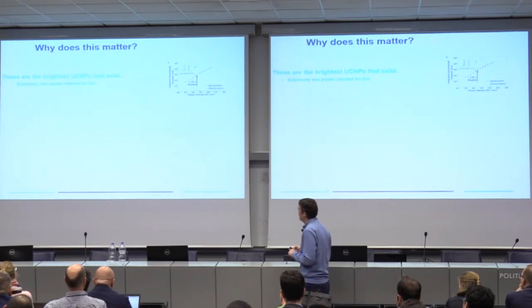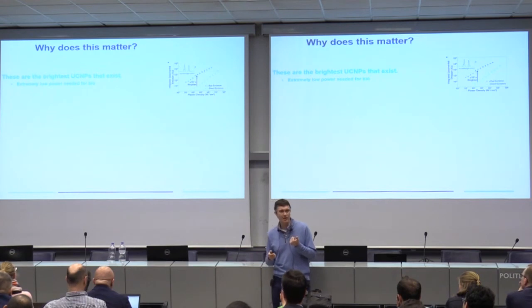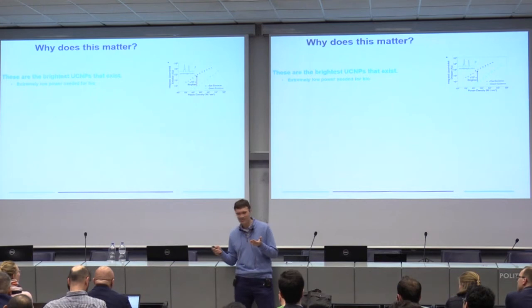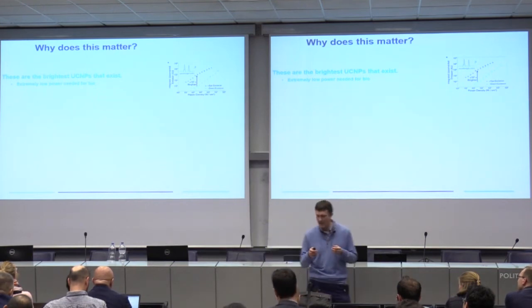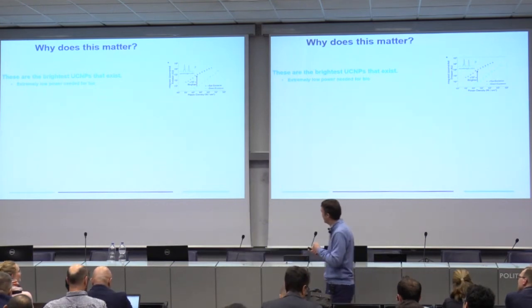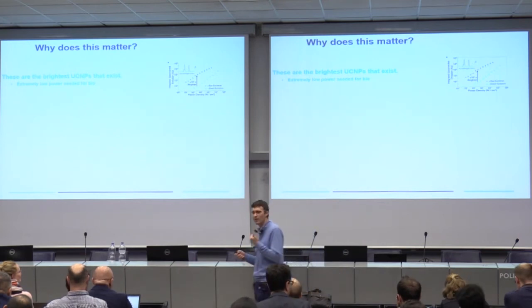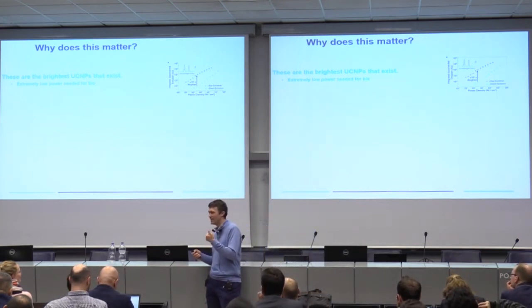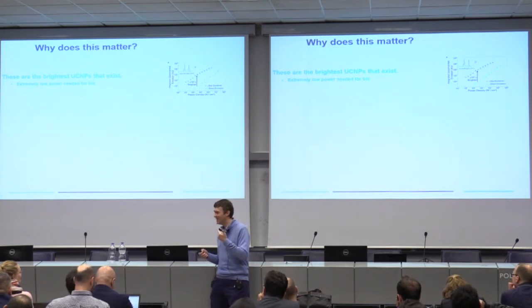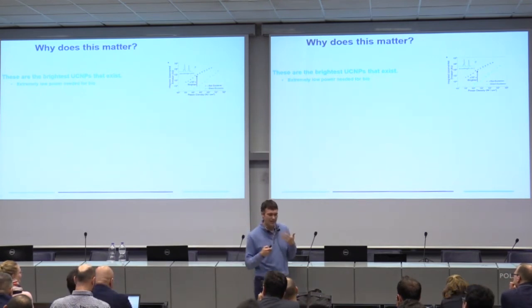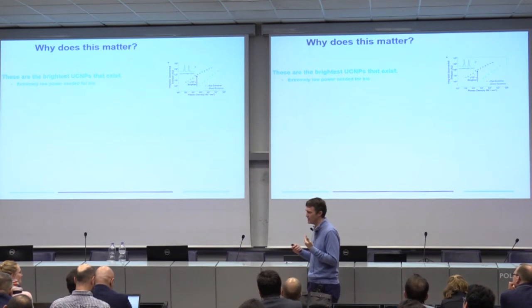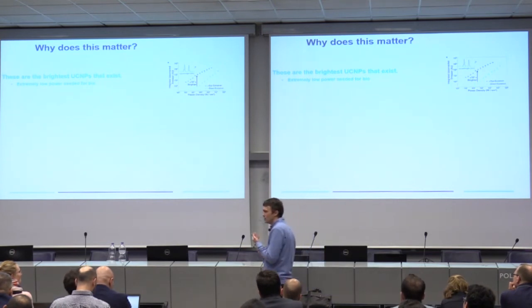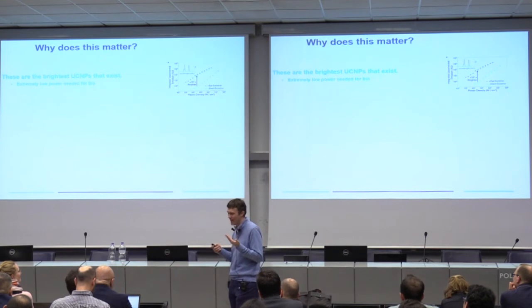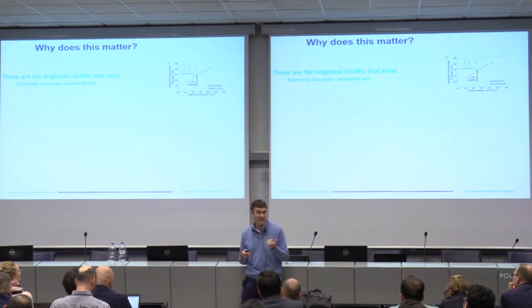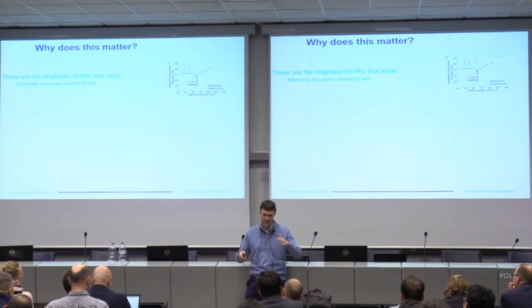Why else does it matter? Well, first, these are the brightest upconverting materials that exist, period. So that's pretty exciting. So we're trying to figure out what to use them for. I will tell you right now, I'm talking about all the good things. There is one big downside, which is all the downsides that we have with dyes now matter again for this. So the antennae idea was great, but maybe there are better antennas that aren't so air sensitive. Basically, if you introduce these to oxygen, they photobleach, and that's the downside. For a solar cell, though, that might not actually matter that much because you encapsulate those things anyway and you keep the oxygen out.